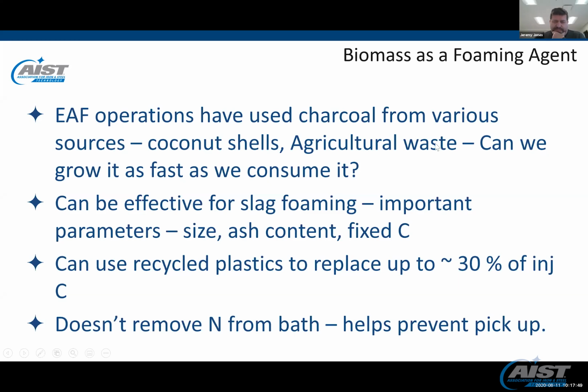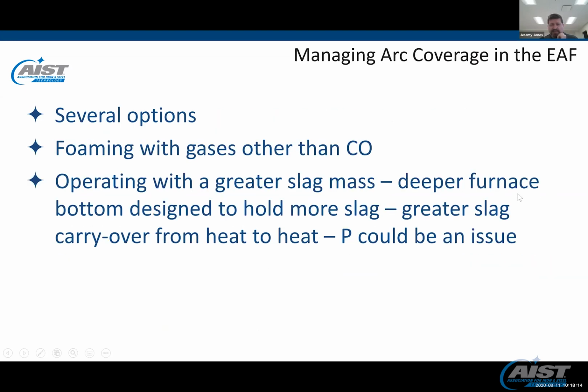And of course, with all of these things, slag foaming is important. We don't actually remove nitrogen from the bath through slag foaming operations, but we definitely prevent the pickup of nitrogen, and we prevent air nitrogen from passing through the arc and getting ionized and traveling back into the steel bath.